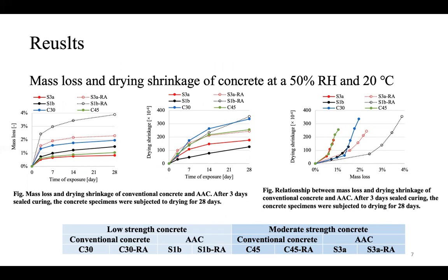The second figure shows the drying shrinkage value. It is worthwhile to point out that the alkali-activated concrete with natural aggregates had a lower shrinkage value than conventional concrete with a similar strength class. It means alkali-activated concrete doesn't necessarily have a higher drying shrinkage than conventional concrete.